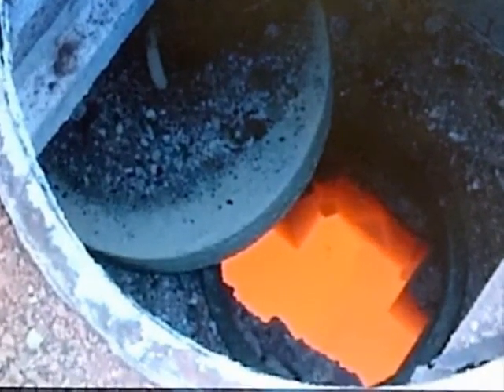How long will your green bricks stay there until they're proper bricks? They'll be in the kiln for about five days. To ensure that the enormous kiln is working to maximum capacity, it's been given handy portholes to add fuel. Those are glowing bricks, are they? Yeah, 1,030 degrees. The process starts with them — as they approach the fire they gradually dry out, and then the temperature rises up to 1,000 degrees where they fire properly, and then there's a cooling process, and the whole cycle takes about 12 days. The fire moves around the kiln, the bricks are stacked all the time, and we load the green bricks in ahead of the fire, and then take out the fired bricks behind the fire. It's a continuous process.